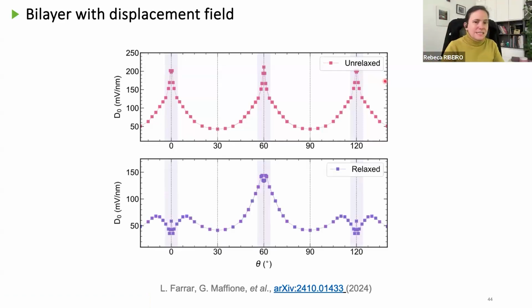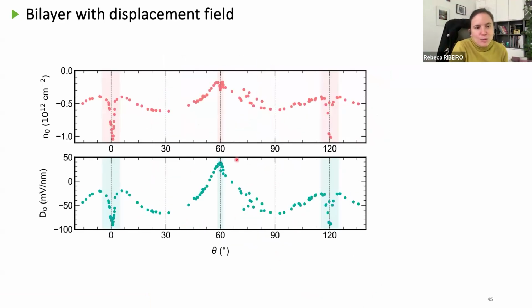So now if you relax the system, you can see that this curve now resembles a lot more our experimental curve. And in fact, what we are seeing around here, that I have been promising to explain to you for a while now, is in fact the commensurate state. So this is the electrical response to that stretching inside the moiré cell that I explained at the beginning. So this is how the system is responding electrically, or how the band structure is responding, how the localization of your wave function is also responding to that intrinsic stretching of graphene with respect to boron nitride. So